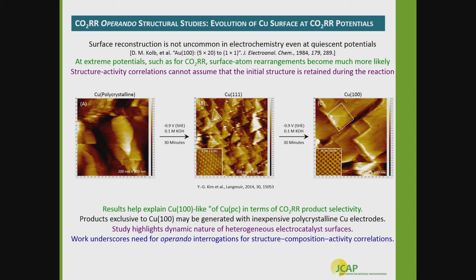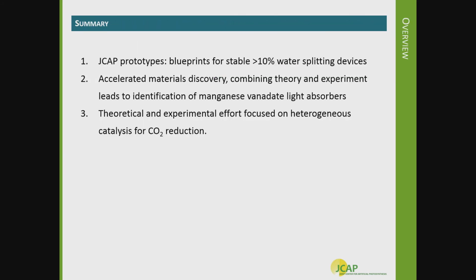And this actually broadly helps us to understand what has been noted in the literature previously, that the chemical activity for CO2 reduction of polycrystalline copper was very much like that of 100 copper. And indeed, we can see that's because under electrochemical operating conditions at room temperature, the surface transforms on the nanoscale to locally 100-like structures. And I think this is just the tip of the iceberg, so to speak, on understanding in detail, at the nanoscale and under operating conditions, the complexity of CO2 reduction.